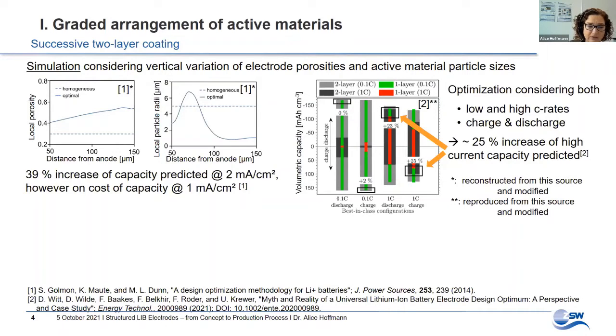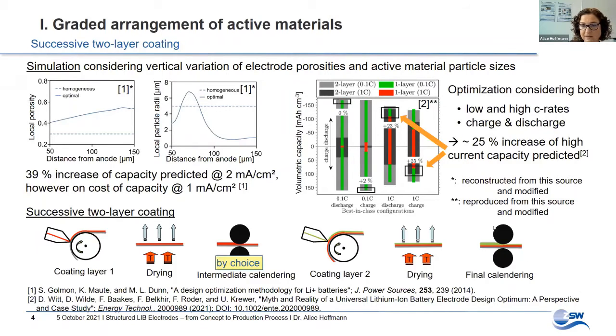Although the simulations are confined to the regarded systems and they conclude different trends for an optimal structure, they predict large improvement by a graded arrangement compared to a homogeneous single layer arrangement. A large increase of areal or volumetric capacity at higher current density is predicted, which can be reached with or without compromises at low current densities. In practice, the graded arrangement can be realized by a successive coating of two distinct suspensions. After the first layer is coated and dried, the composite can by choice be intermediately calendered, or the second layer is coated directly on the first one. By the final calendering, the two-layer composite is densified as a whole.